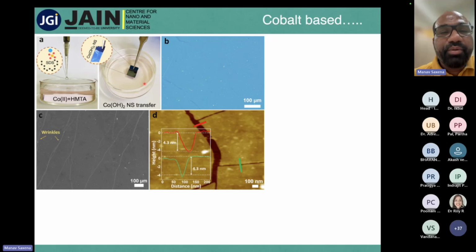So we can make a cobalt hydroxide film the size of the complete Petri plate, which we can scoop onto any substrate, whether a silicon wafer, platinum, or gold, wherever you want to transfer it. In figure B, you can see the optical images where the film covers the complete area, with only minor cracks visible. In figure C, the SEM image, you can see wrinkles due to the transfer process. The wrinkles also suggest that the film is flexible.